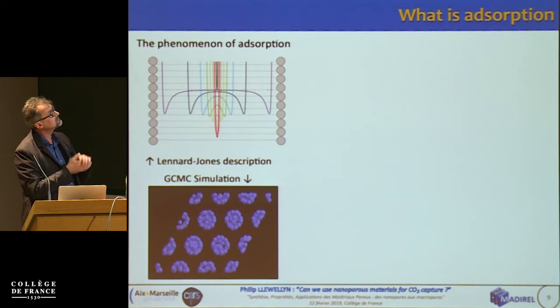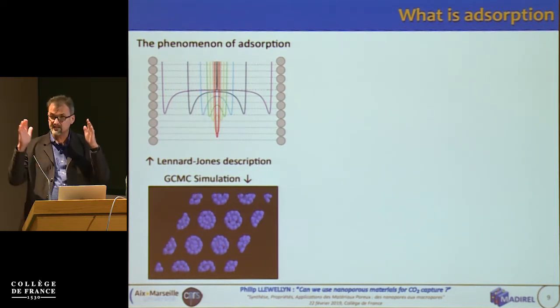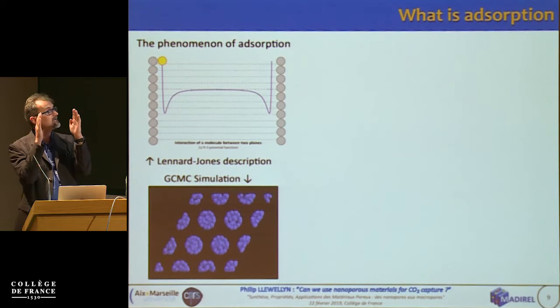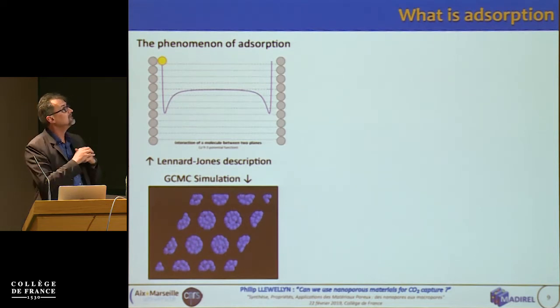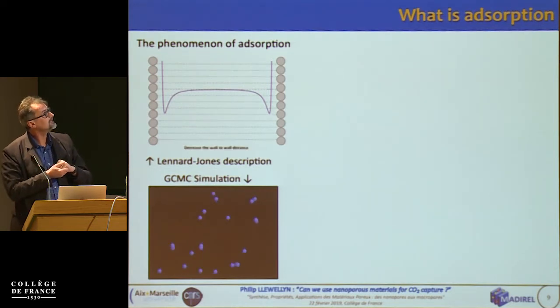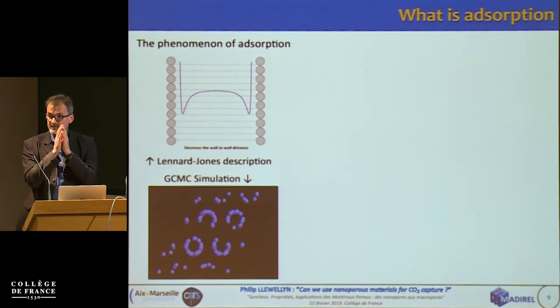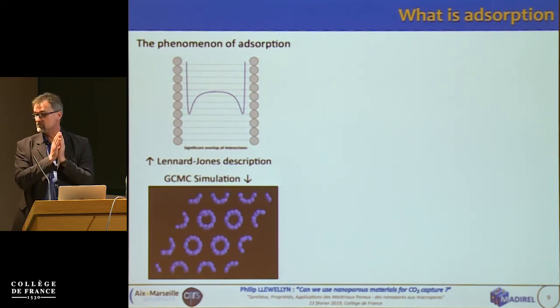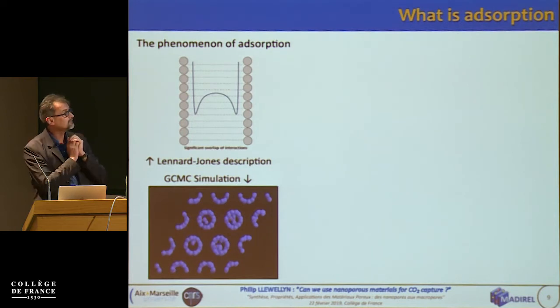Okay, this is the whole system as we close slowly but surely. But you can see that at some point the two walls will come together, and when the two walls come together, the minimum potential energy that we see here will overlap, and we'll get quite strong interactions inside the pore. And this is why nanopores are interesting for adsorption.